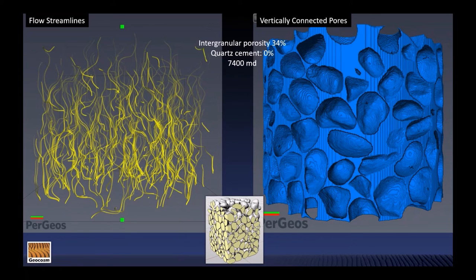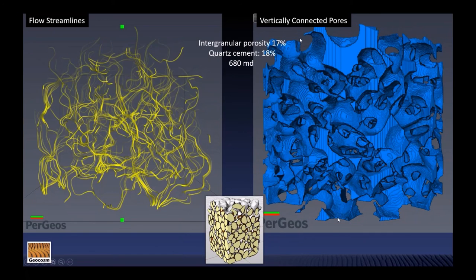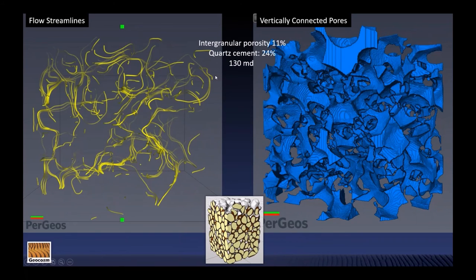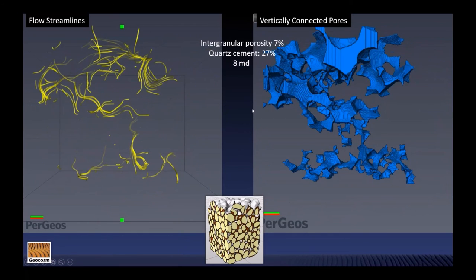with quartz cement. So here, now we've got about half of the pore space filled in with quartz cement. Notice our spaghetti is getting much more tortuous, and we've dropped our permeability by about an order of magnitude. We'll put in some more quartz cement. Now we're down to about 130 millidarcies, much more tortuous pore space. And then here at this point, we're down 3 orders of magnitude from where we started. We have a very discontinuous pore space.